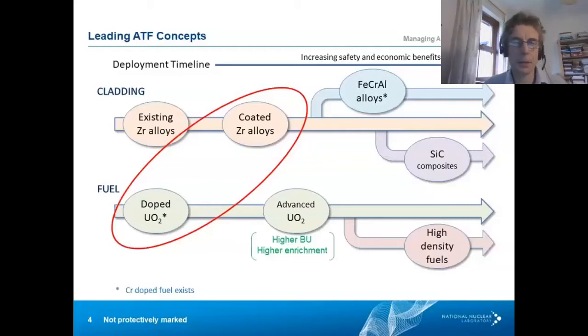The fuel aspect really is that developments are proposed there to improve the economics and to make accident-tolerant fuels more attractive for reactor operators. And there we're looking at doped UO2, advanced UO2, which allows us to go to higher burnups and higher enrichments, thereby also reducing the amount of fuel we need. And finally, continued investigation in higher density fuels, which allows better irradiation performance.